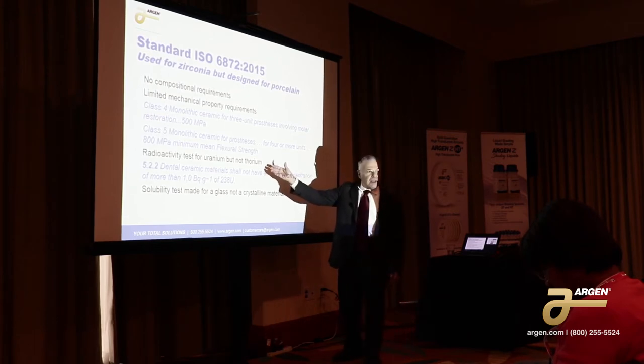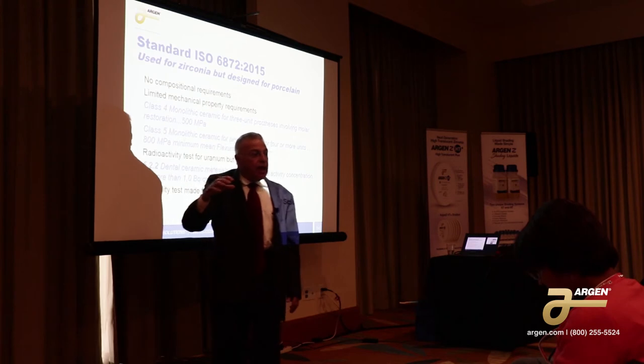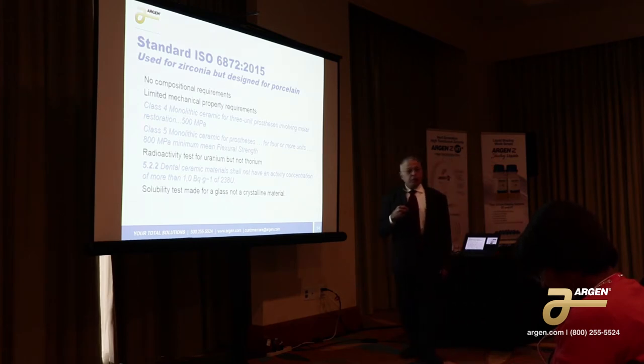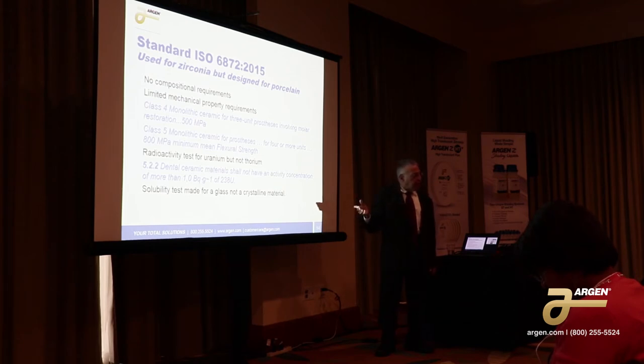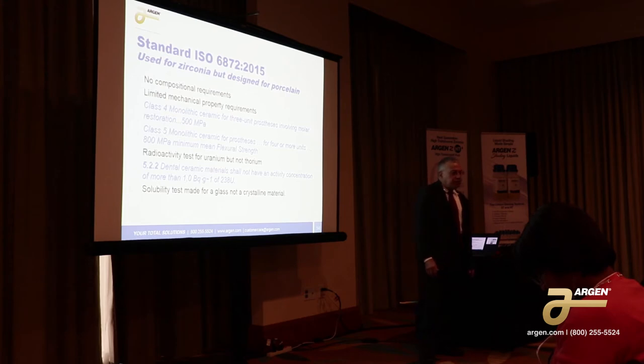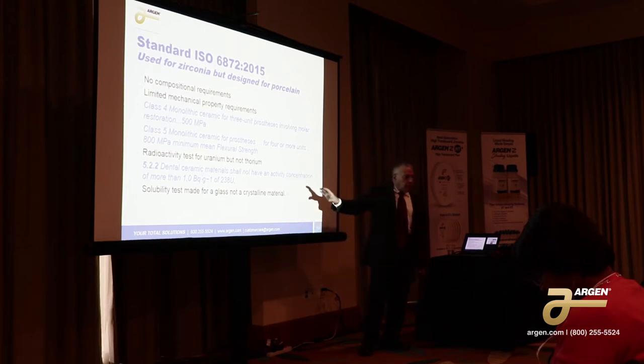It has a radioactivity test for uranium, but not thorium. In the 60s when they first started developing dental porcelain, they used uranium dioxide as a fluorescing agent. Then the FDA said they didn't want uranium in people's mouths, so it was replaced with cerium. But the zircon material is loaded with not only uranium, but also thorium. They don't talk about thorium. The solubility test is made for a glass, which in most cases dissolves much better than a crystalline ceramic, so it'll always pass. We're dealing with a situation where you have to rely upon the company to give you a good product, because you can't rely upon the standards committee and you can't rely upon the FDA. The ADA came out with their own standard, and it's even worse.